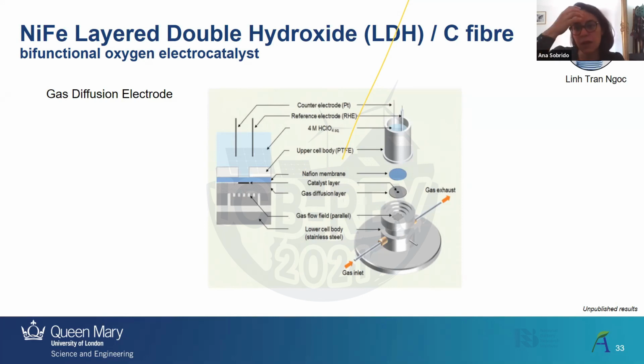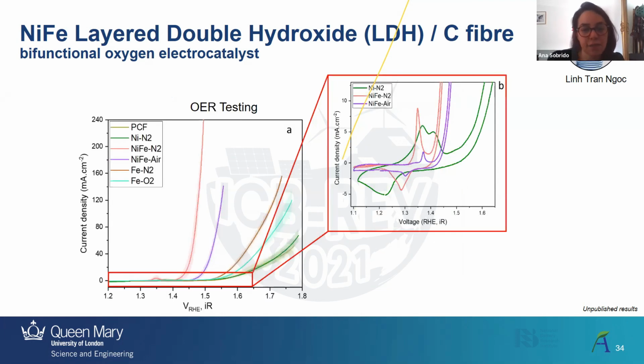So this system allows us to study our electrodes for oxygen evolution and reduction. I have to say that I'm only going to present here the results that have to do with the oxygen evolution, because I think they're the most interesting ones, but we also have oxygen reduction. So this material is actually a bifunctional oxygen electrocatalyst. It can do oxygen reduction and it can do oxygen evolution. That's what a cathode in a metal air battery would need to do.